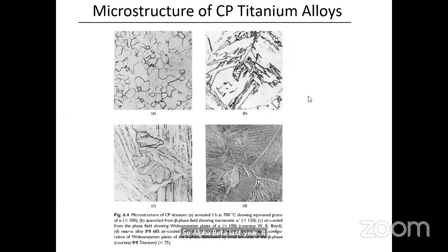So these are the microstructures of the CP titanium. The first one shows equiaxed grains, if it is annealed at 700 degrees. If you quench from the beta phase field, just like if you take steel into the austenitic region and quench, you will get martensite. Similarly, if you heat the alloy to the beta region and quench, you will get a martensitic kind of microstructure. You see here a needle kind of microstructure.